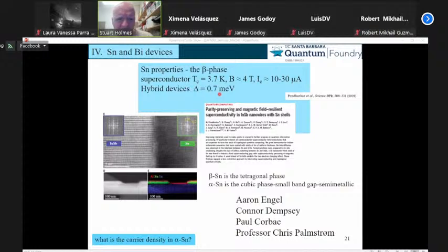So tin, you think of tin as being metallic. In the beta phase, it's metallic. It goes superconducting. It has a transition temperature of 3.7 Kelvin, so below that, it goes superconducting. It has a critical field of about 4 Tesla, a critical current of 10 to 30 microamps. So it's a reasonable material. It's got quite a small gap, Delta equals 0.7 meV. So when it's in the superconducting phase, it has a small gap.